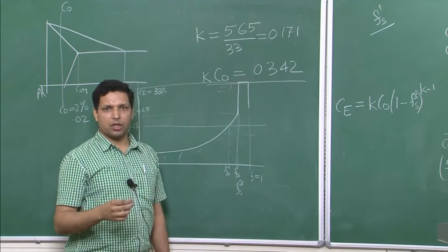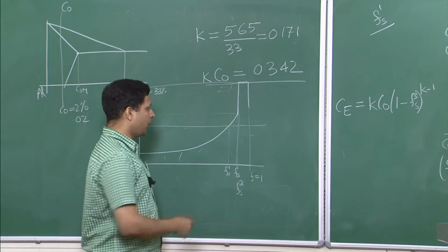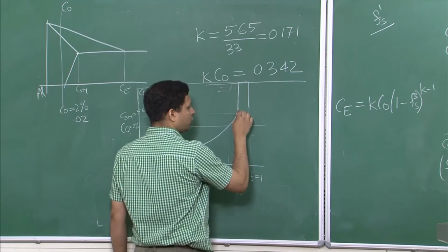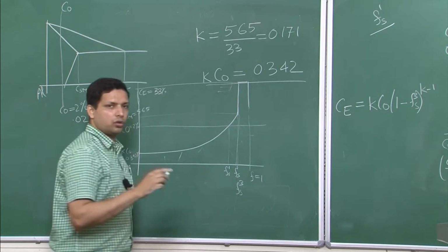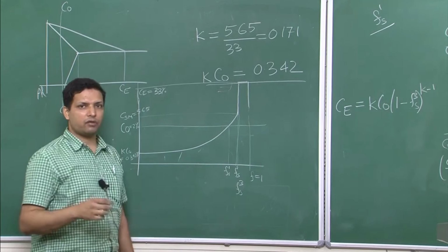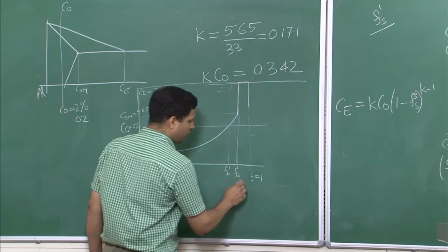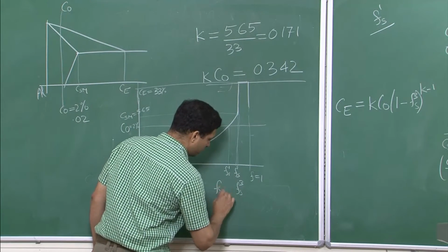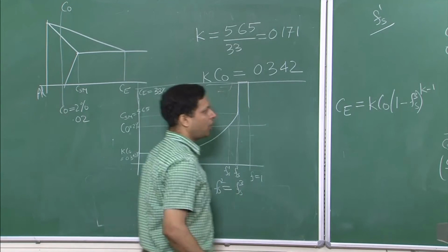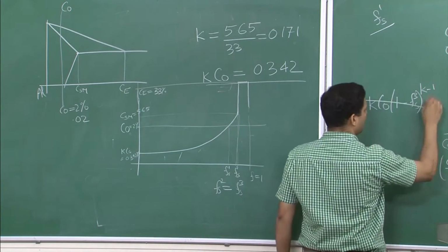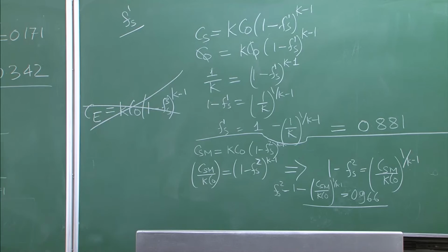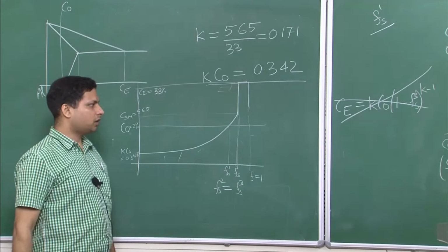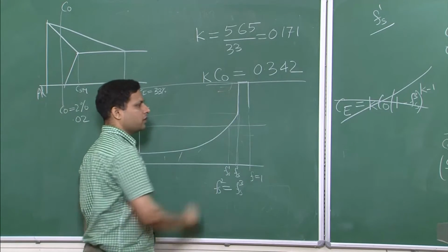So both of them solidify simultaneously, and therefore the fraction at which you see CSM is the same fraction at which the liquid solidifies, and therefore FS2 would be equal to FS3, and this equation is not valid for finding the fraction at which concentration reaches CE.